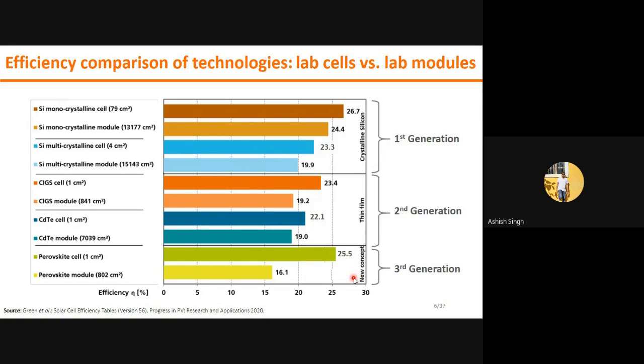Here we are comparing the cell level efficiency with module level efficiency of all these solar cells. We can see silicon-based solar cell gives the highest efficiency, about 26.7% on the cell level. This is lab scale, and this module is also on the lab scale level, giving 24.4%. While if we see the perovskite solar cell, its cell level efficiency is 25.5%, but the module level efficiency goes significantly down. That means the mismatching between each cell is different than the mismatching between the silicon-based monocrystalline cells. Due to this, till date, only first generation and second generation solar cells are commercialized.